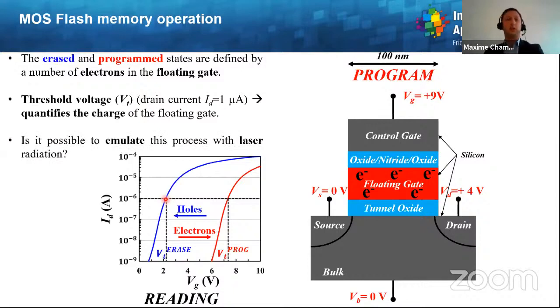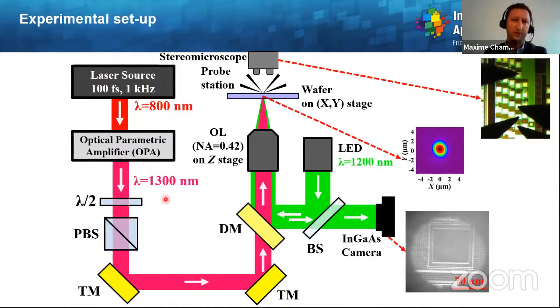So now the main question is: is it possible to emulate this process with laser radiation? To answer this, we have developed an experimental setup. I will not go too much into the details, but it relies on ultra-short laser pulses, so 100 femtoseconds at 1.3 micron wavelength. Then we control the energy by means of a half-wave plate and a polarizer, and focus the beam onto the microelectronic wafer. And besides, we have two diagnostics. First, a stereo microscope in order to make some 4-point probe measurements and eventually program and erase the device in situ. And also here, represented in green, sorry, a microscope working in reflection for observing the microelectronic device and inducing the plasma near the flash memory.